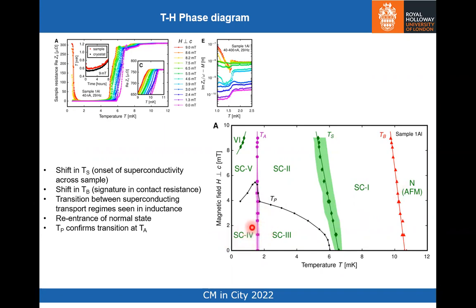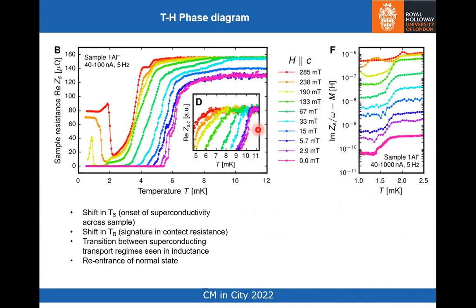There's the shift in the contact resistance transition, the transition between different transport regimes, at 1.5 millikelvin, which doesn't shift. The labeling is interesting, but roughly speaking, here is the re-entrance of the normal state, and here is the signature of the onset of persistent currents, which you see has a quadratic type field dependence, and then hits the TA line, and you see that kink then also confirms the existence of a change in the superconductivity at this characteristic temperature TA.